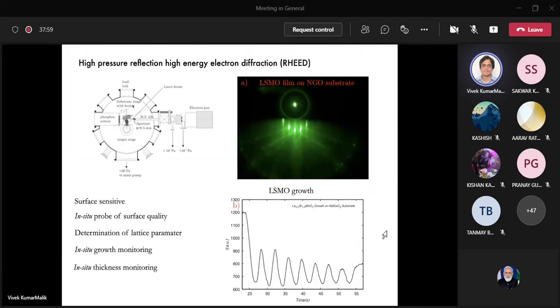And what you essentially can do is also, using something called electron diffraction, you can grow it layer by layer. Like one unit cell is formed, then a second unit cell, and you can always control where you want to stop it. So this is an electron diffraction pattern on a camera. You take an electron gun at the surface, it gets diffracted, and then you see these diffraction spots. You will study X-ray diffraction or electron diffraction later on in various courses. So this gives you the symmetry of the atoms of your surface. This spacing between these spots is directly related to the interatomic distances.